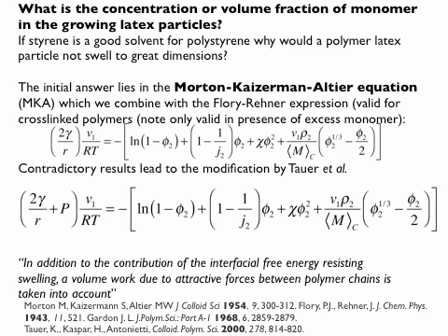So it's like a fitting factor almost. You could also argue, which is not displayed here, that okay, imagine I have a sphere with 100 sulfate groups on it, and these sulfate groups are derived from my initiator end groups, and they have a certain interfacial tension. The interfacial tension is not very high because these sulfate groups lower the tension between the hydrophobic particle and the water.